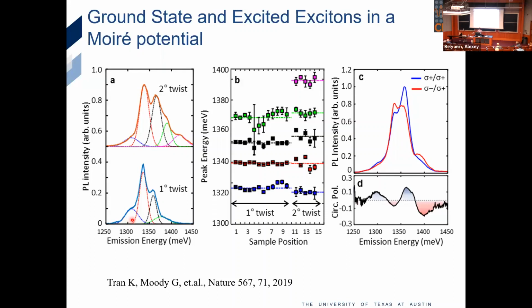And frankly, ideally, if I have the choice, I want to work with chemically grown samples. I've shown you the STM image. It was actually pretty uniform. Why do I still torture my students, asking them to stack them? It's because the CVD grown sample has a lot of point defects that make the transitions very broad. Then they just kind of merge into each other. I don't see these discrete states anymore. So that's why at the moment, we're stuck with the mechanical stacking method. If our friends in chemistry figure out how to reduce the defect level, and give us more uniform Moiré superlattices with sharper peaks, that'll make our life so much easier.